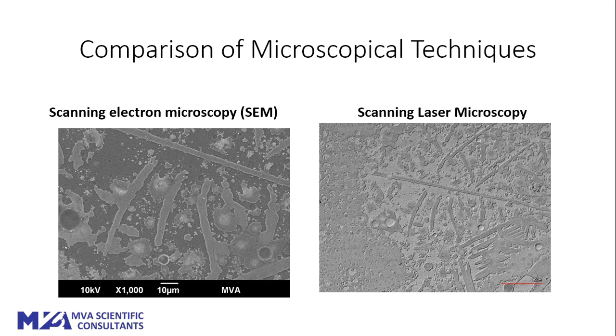This next slide shows two images side by side — the SEM image on the left and the laser scanning microscope image on the right — showing the same features. You can see three vertical lines and a horizontal one. In the laser microscope image, larger areas show various contrast in color: the darker area is the original surface, and we can also see pits that are more clearly visible than in the SEM. We are seeing pitting and considerable areas where the surface of the glass has been removed.